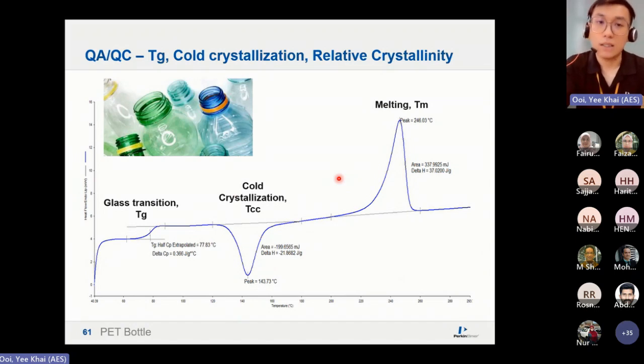Now, this is a slightly tricky example. You have your PET, which is a semi-crystalline material. As I mentioned, semi-crystalline material will have TG, because the amorphous part of it is represented by the TG. Then you have your cold crystallization, especially when you heat up slowly, for example 10 degrees C per minute, the conventional heating rate. After it passes through TG, free volume increases, and the molecular chains can now move around. The general rule is, if a material can go to crystalline form, it will go to crystalline form, because crystalline form is more stable than amorphous form. Hence, even when you are heating, the molecules inside will start to arrange themselves into an ordered manner.